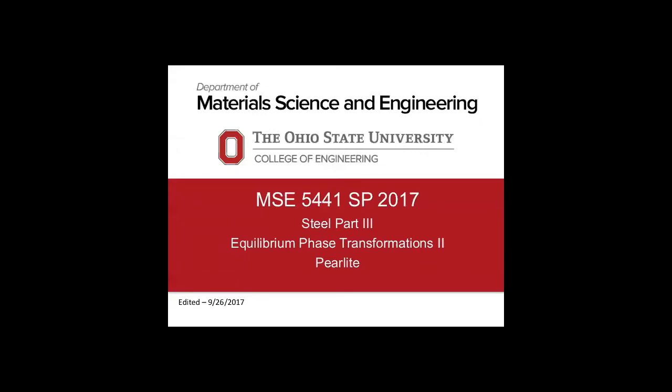So that displacive mechanism just changes the morphology, but it's still the same composition, same everything else. It's still ferrite, and the composition's the same as the proeutectoid ferrite. There's still carbon being rejected, so all that's still happening. It's just that the actual mechanism of the transformation isn't purely diffusional. There's also shear associated.